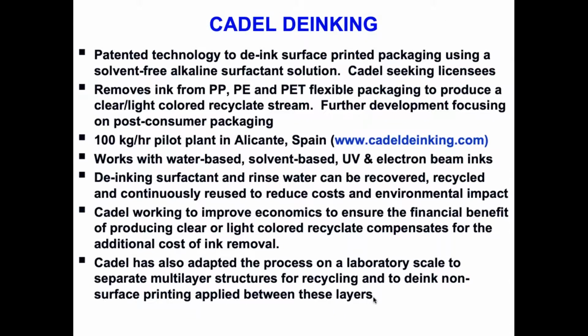Secondly, Cadel de-inking in Spain. This is technology to de-ink, originally surface printed packaging using a solvent-free alkaline surfactant solution. Cadel's looking for licensees of the patented technology. Removes ink from polypropylene, PE or PET, gives a light-colored recyclate or clear recyclate, and their development now is focusing on post-consumer packaging. They have a pilot plant in Spain. It works with water-based and solvent-based UV and electron beam inks. And the de-inking surfactant and rinse water can be recovered and recycled.